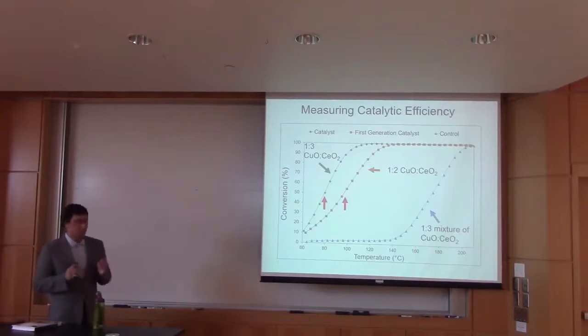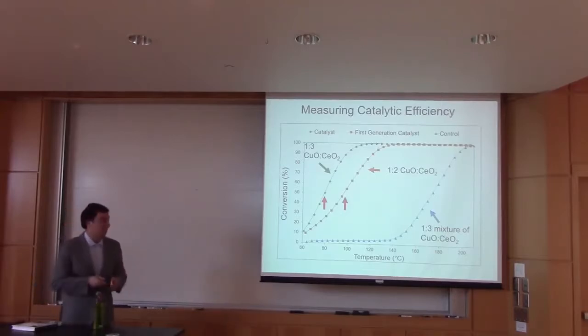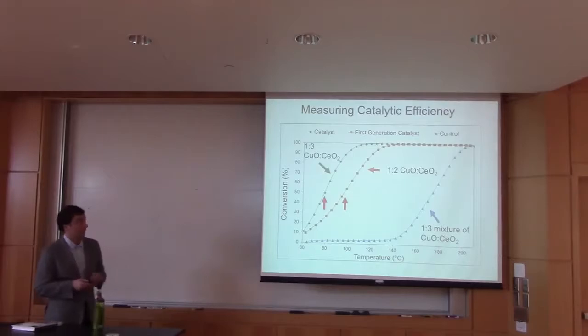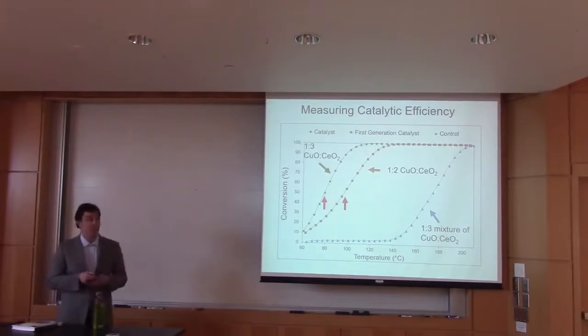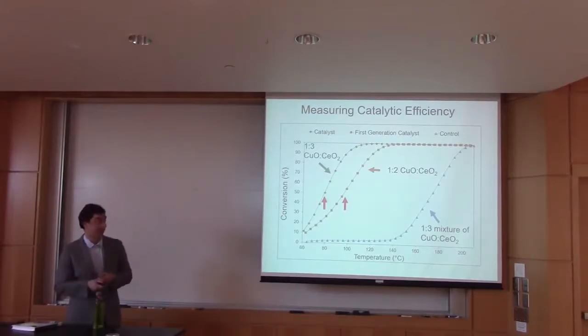But also, the much more important thing is we have been able to create a more efficient catalyst by controlling that interfacial area and that copper oxide domain. And the really cool thing I think about this work is we've created a catalyst with less copper in it compared to the previous catalyst and have higher efficiency even though we have less of that active metal, just by controlling that domain size and that interfacial area.